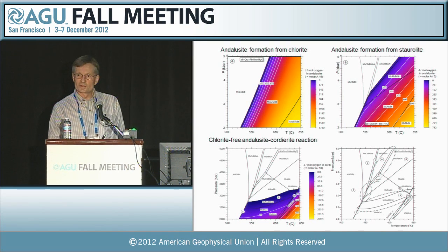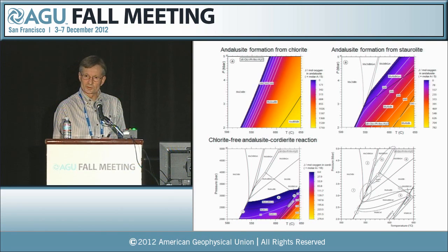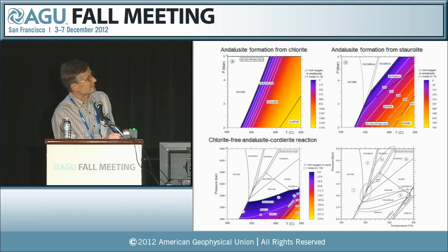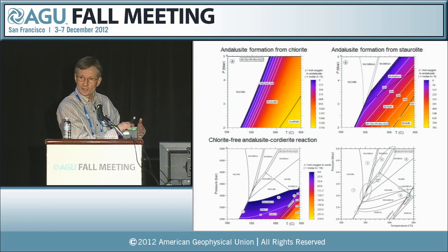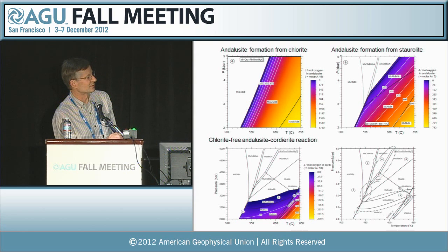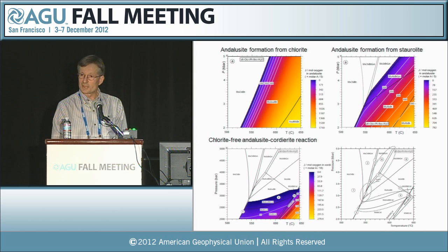And you can see that the rate of buildup of reaction affinity is dramatically different between the three. The prediction in terms of overstepping is that this one should give the least overstepping because it builds up the energy needed to overcome the kinetic barriers to reaction most rapidly. This one is extremely low, to the point where possibly it doesn't happen at all, or if it does, it might be very strongly controlled by kinetic factors.